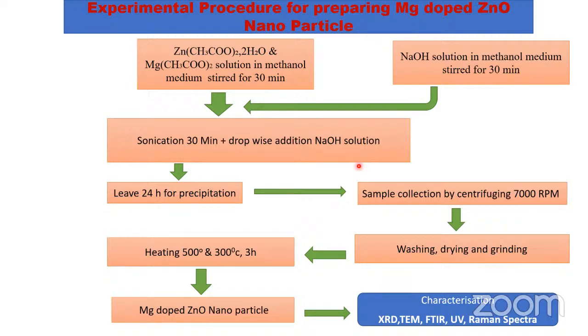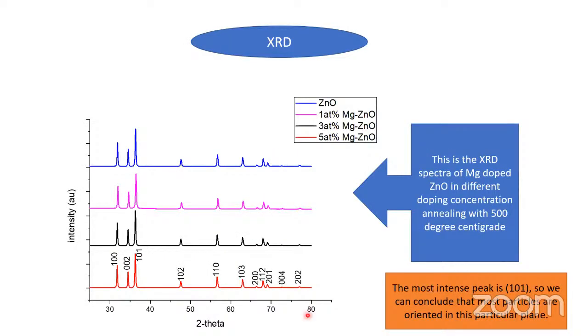Finally, when precipitation is completed, we collect it by centrifuging at 7,000 RPM. Then we do cleaning and washing. We wash it 2 times with double distilled water and 1 time with methanol. After that, we collect the Mg doped ZnO nanoparticles, and we heat it for 3 hours at 300 degrees and separately heat it for 3 hours at 500 degrees centigrade. After that, we do characterization like XRD, TEM, FTIR, UV, Raman spectra, etc. Now this is the XRD diagram of the 500 degree annealed Mg doped ZnO nanoparticles.